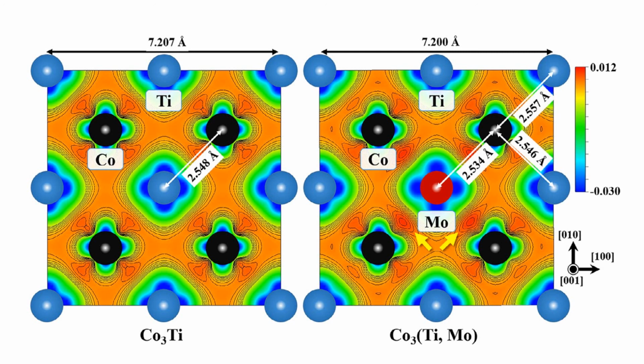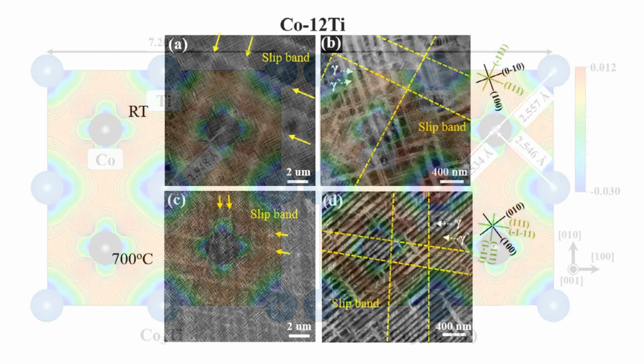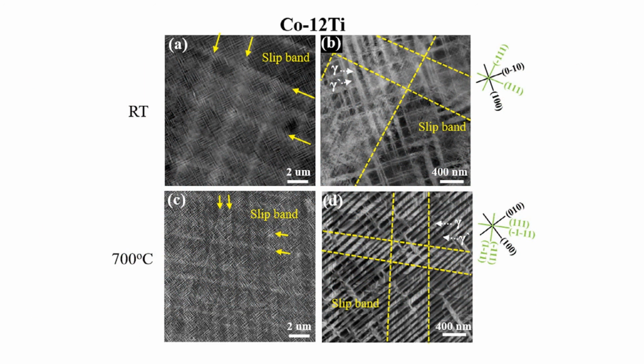Using electron channeling contrast imaging, we observed interrupted slip bands in the cobalt, titanium, molybdenum alloy, deformed to a strain of 6%, which led to enhanced strain hardening, in contrast to extended slip bands along 111 planes in the cobalt, titanium alloy. Interrupted slip band formation in cobalt, titanium, molybdenum could be explained by rapid exhaustion of dislocation sources and a higher energy barrier required to cut the gamma prime precipitates.